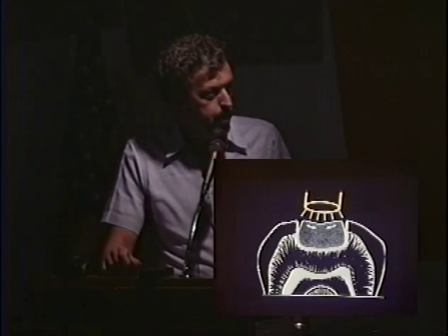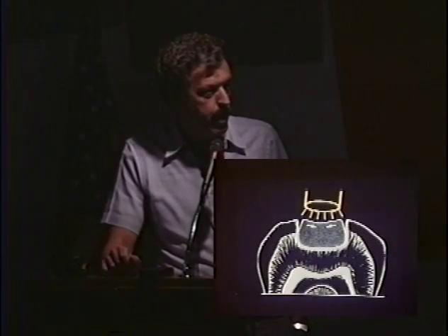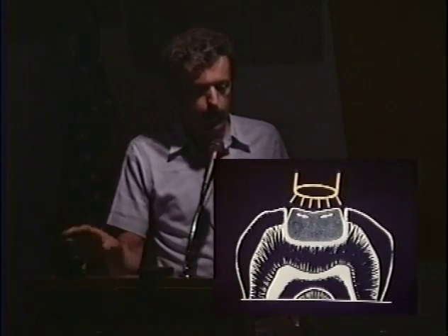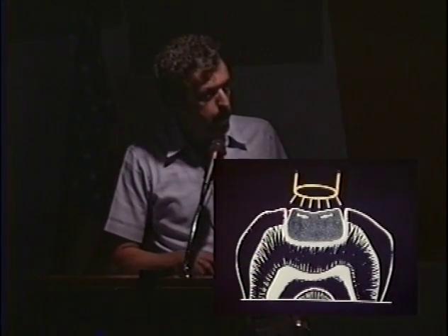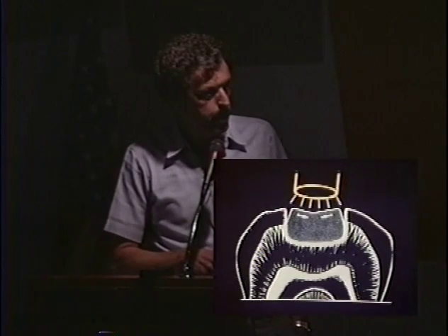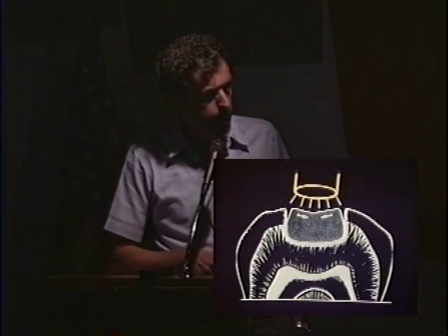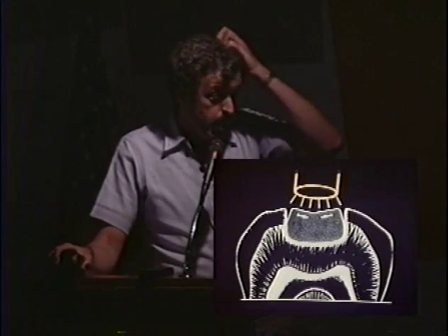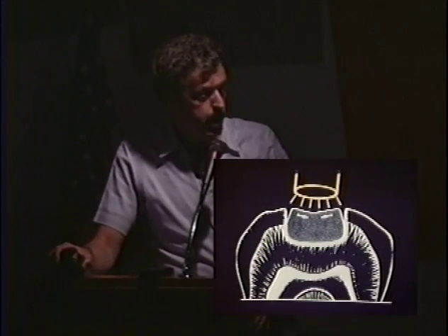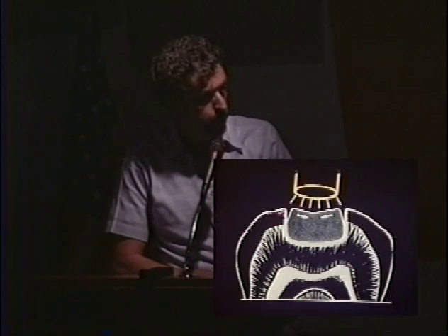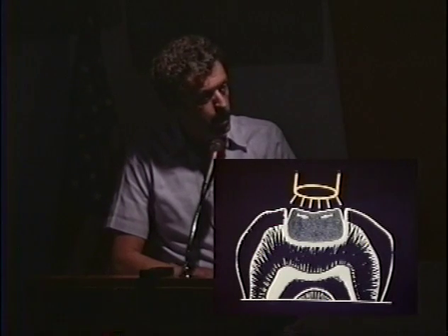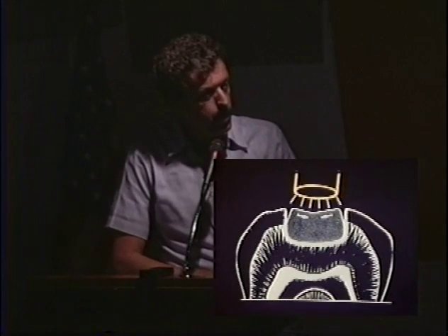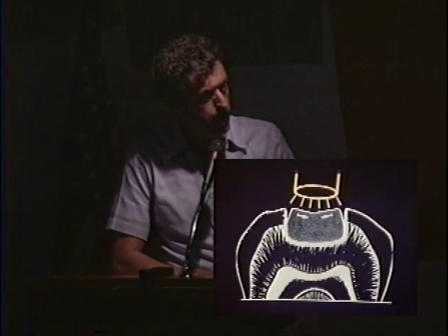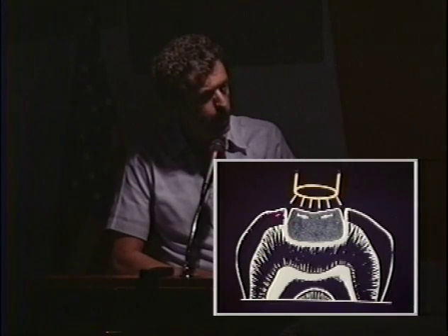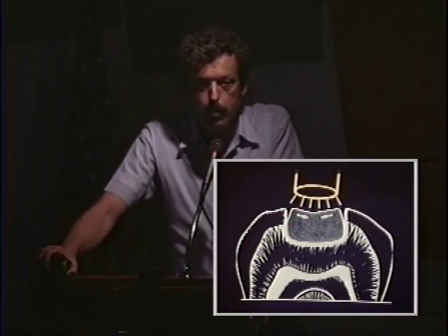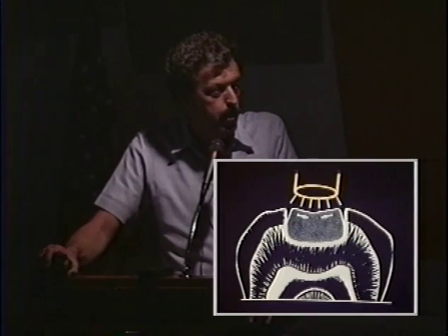Now there's the inherent problem that happens when you put in a posterior composite. It shrinks by volume about 4%. So it tends to pull away from the margins. Now when you get this margin pull away here, you're wide open for trouble. Now whether this happens clinically or not is questionable, because composite can viscous flow during its polymerization, and it can in fact remain in contact with the enamel during its polymerization. So whether or not it pulls away is questionable, but if it in fact bonds to the enamel, you could conceivably break enamel rods, because we calculate up that the polymerization stresses there are about what it takes to cleave off rods.